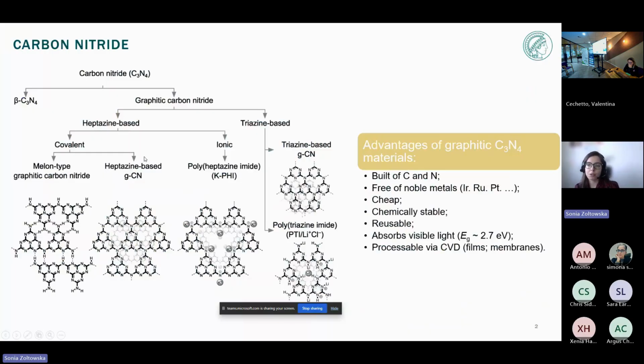And why is that? Because this material is built only from carbon and nitrogen, it's free of any noble metal, it's relatively cheap as a catalyst, it's chemically stable, can be reused, absorbs visible light, and as you will see further, it can be processed via the CVD method, so we can obtain films or different types of membranes, depending on what we want to do for which type of application.